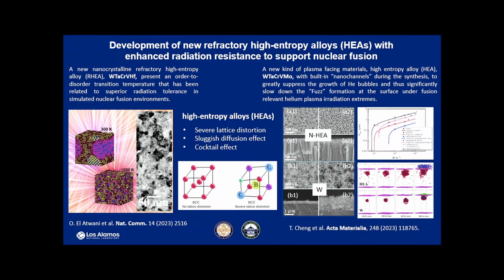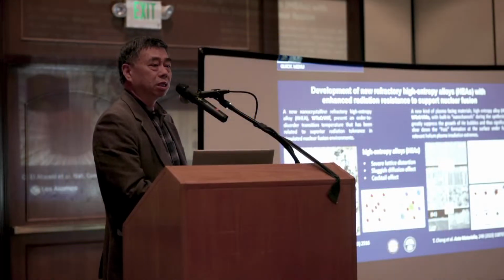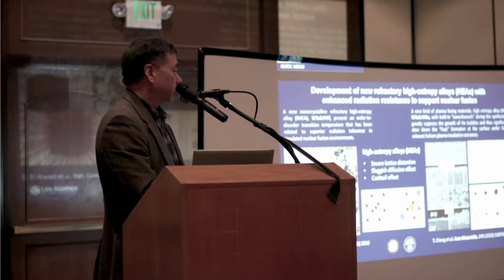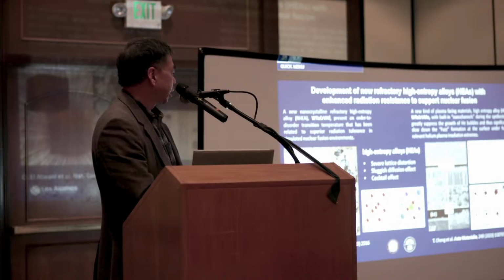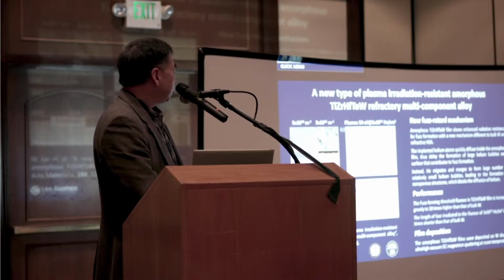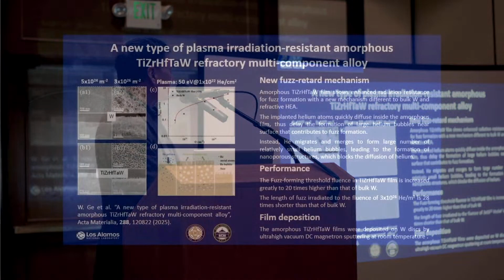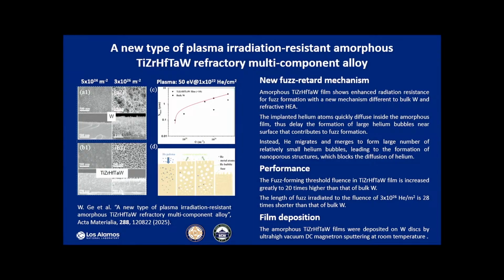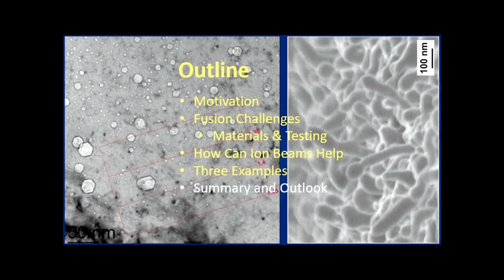Similar to the nano-channel tungsten, we were able to make a nano-channel HEA. And this further reduces the fuzz formation process compared with the nano-channel tungsten case there. Even with an amorphous structure, which is not a high entropy alloy but just amorphous elements together, you can also delay that process as well.